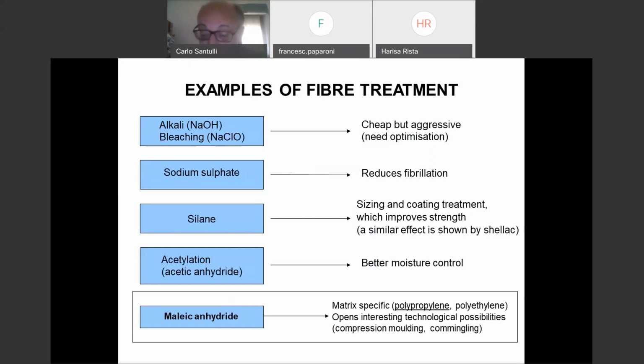So this is a limitation in terms of production, and also in some cases for use. Then there are some specific treatments. For example, maleic anhydride is used a lot for some matrices which are of particular use in, for example, the automotive industry, because the automotive industry is very fond of using polypropylene or polyethylene. And therefore, you can make these plant fibers more compatible with polypropylene, polyethylene by using the maleic anhydride. This is called maleinization of fibers.